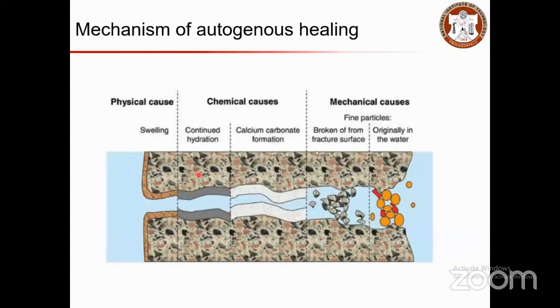So if we look at the mechanism of autogenous healing, we can classify this into three categories. One is physical causes, then chemical causes, then mechanical causes. The physical cause, what happens basically is just the swelling. So some material gets in and it swells. As it is going to react, there will be a continuation of the hydration, and as it is going to hydrate more and more, that is going to produce the hydration products, and those products will fill up the crack. So this is one way. And the mechanical causes, if you have water originally, that is going to break some fine particles, and that is going to accumulate over time, and then that is going to fill up this region.